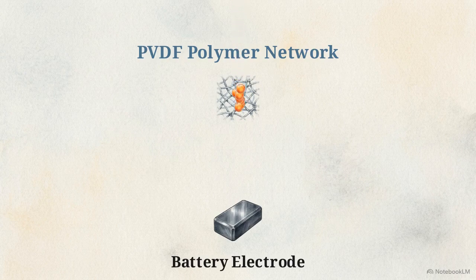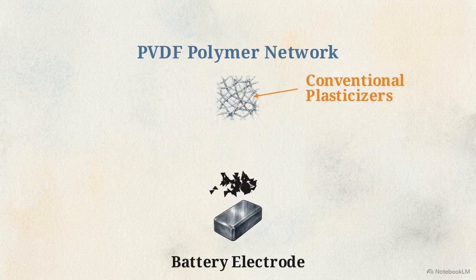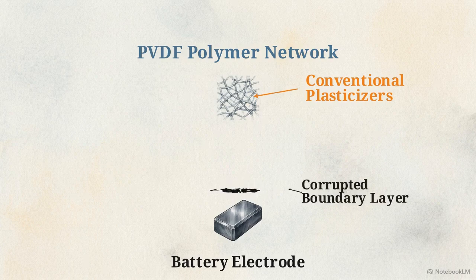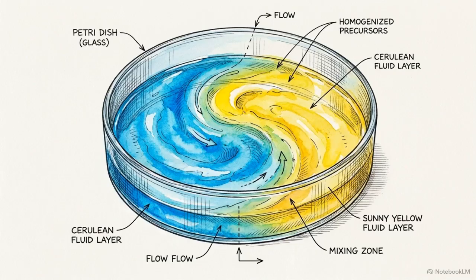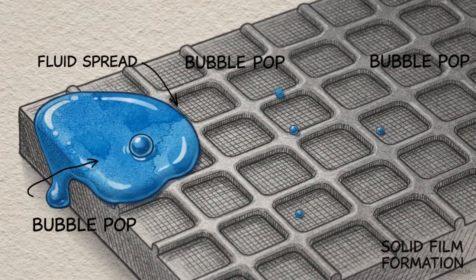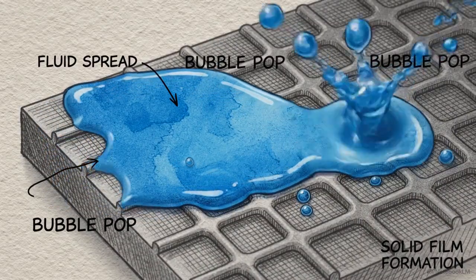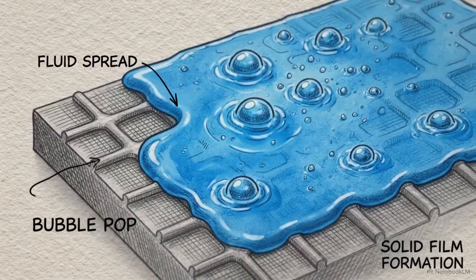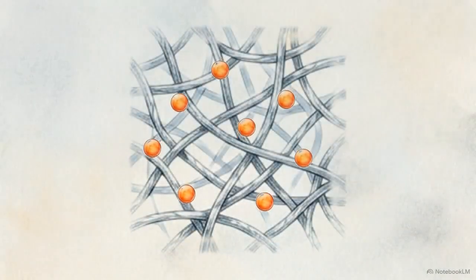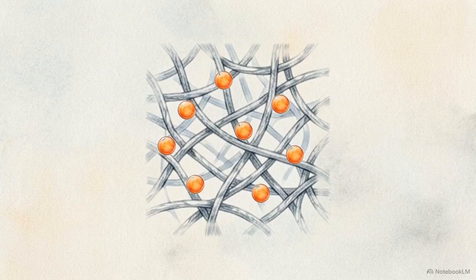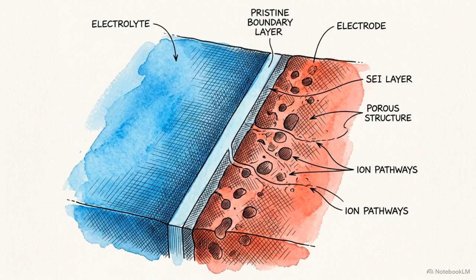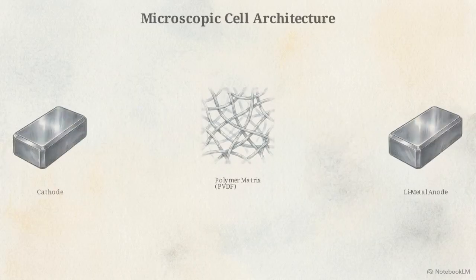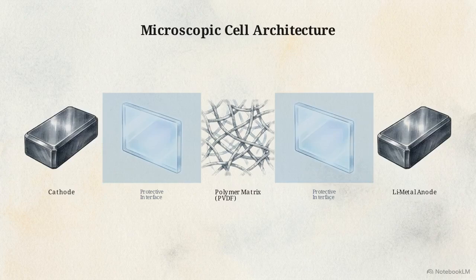The historical point of failure for PVDF electrolytes lies in the conventional plasticizers used to prepare them. These plasticizers exhibit poor electrochemical stability, resulting in continuous parasitic decomposition right at the electrode interface. The research team resolved this by developing a precise chemical strategy termed compatibilizing solvent plasticization. The process introduces a volatile compatibilizing solvent into the electrolyte preparation, temporarily improving the interaction between the polymer and the stable plasticizers. As the solvent evaporates during film formation, the plasticizer is physically locked inside the PVDF polymer network. This controlled evaporation creates a highly stable, lithium fluoride-rich interfacial layer. That boundary layer drastically reduces side reactions at both the cathode and the lithium metal anode.